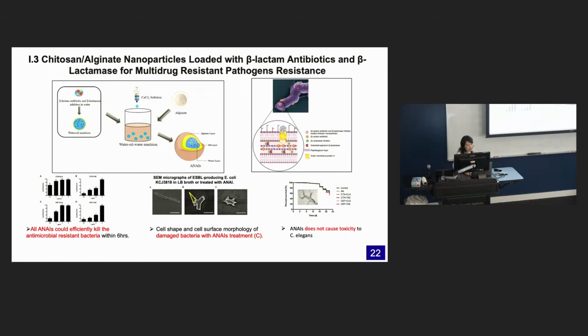The first challenge we met is that the inhibitors and antibiotics are, some of them hydrophilic, some of them hydrophobic. So what we do is we first use vegetable oil to encapsulate, coating the inhibitors and antibiotics, and then we further dissolve them in an emulsion made using nano-chitosan or nano-alginate. Then we found the double layers, right here. So the water-oil-water emulsion system was chosen for this study.